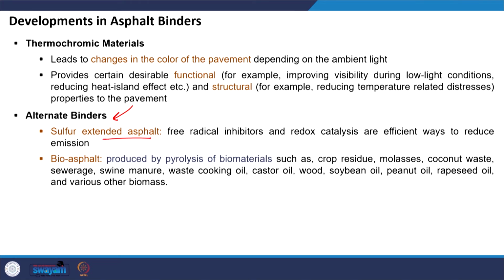The problem with sulfur extended asphalt is that when you heat sulfur to temperatures typically greater than 120 degrees Celsius, there is an emission of H2S gas which can be very harmful. So, this is one of the disadvantages because of which this technology did not become very popular. However, there have been researches that have tried to find effective ways to reduce the emission of H2S gas. So, they have used free radical inhibitors, they have used redox catalysis process, using which the emission of H2S gas in SEA or sulfur extended asphalt can be minimized.